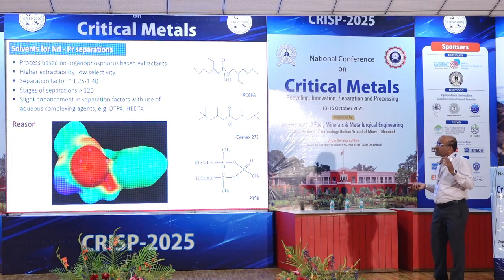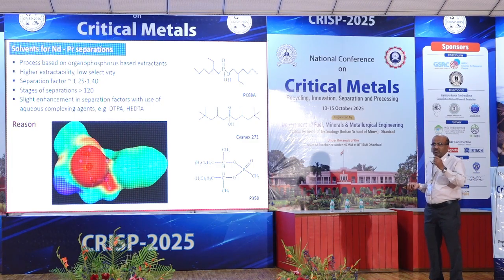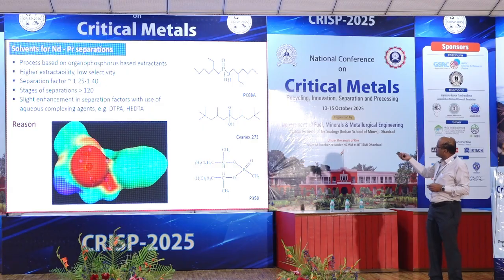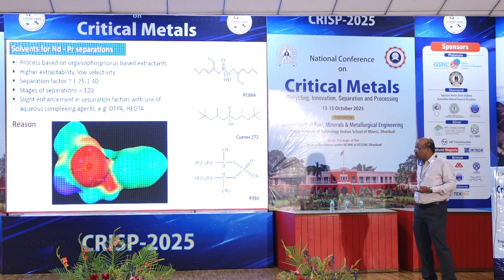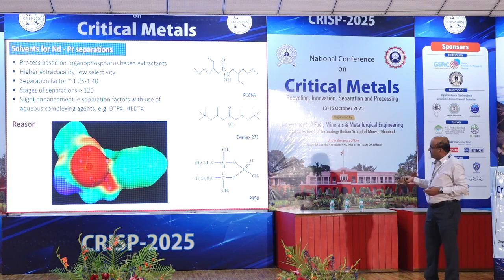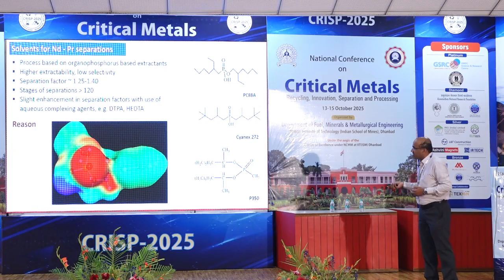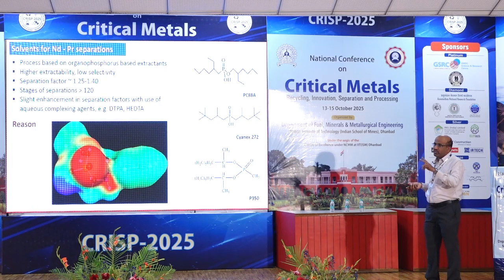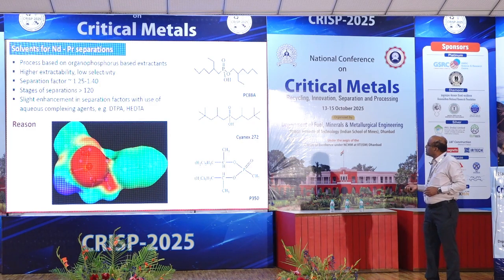F orbitals are almost empty, so you have very weak interactions you have to exploit. But for that exploitation, PC88A or these kinds of molecules are actually not meant for this separation. But because we did not have the molecule, we have used them. See, I have shown the electron density map here. With all these molecules, the electron density is going to the harder direction. It means you want to separate 2 very closely placed metals, and you are using a hard donor. It will not happen. So what we have done?